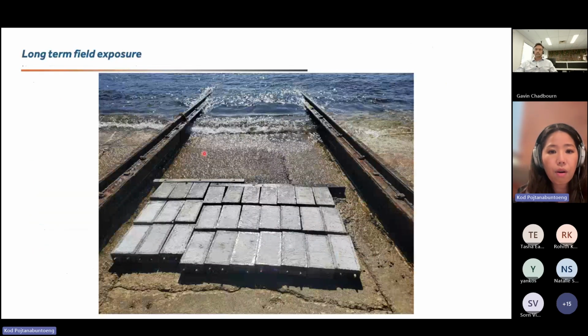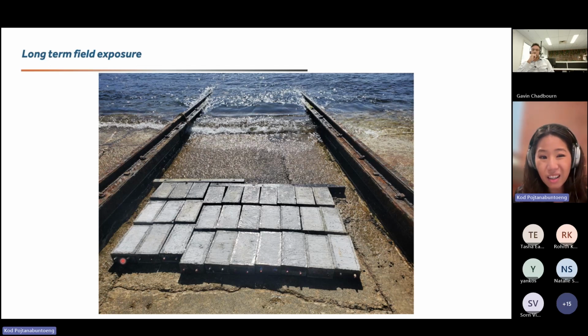These test protocols are currently deployed in the field, as Tasha mentioned. There are 30 of them, 10 mix designs in triplicate. The idea is that every few months we would go in and do the electrochemical measurement on the rebar to see whether or not corrosion has been occurring yet. Of course, it's been only a couple of months, so we don't expect anything to occur yet. It will probably take the time period that was mentioned before. These are deployed in the tidal zone. So this is at low tide. When it comes to high tide, I think the water will come all the way to the top of the test sample here.